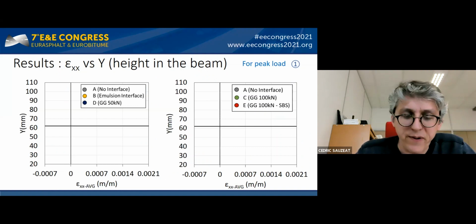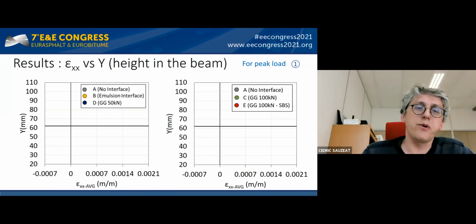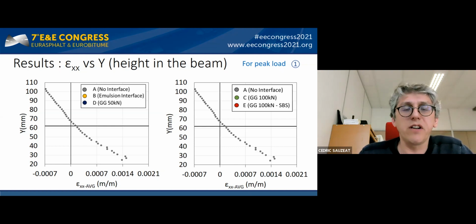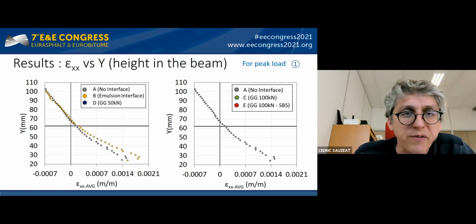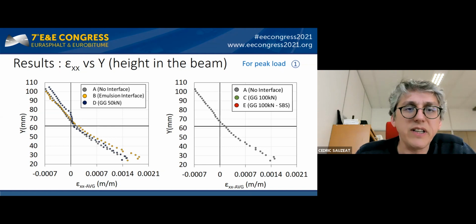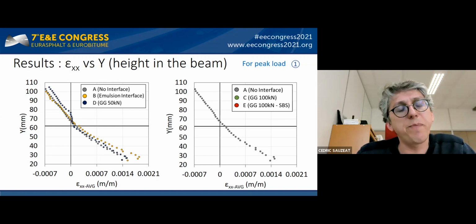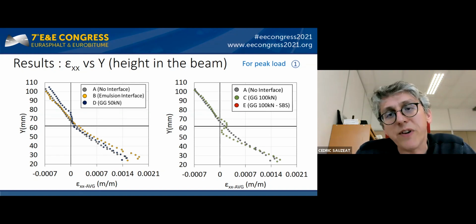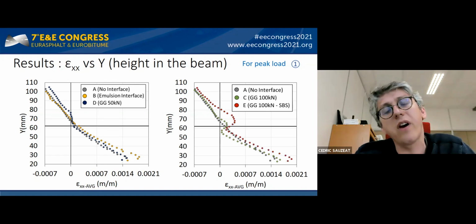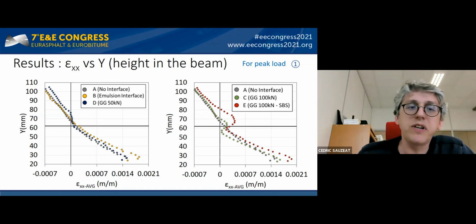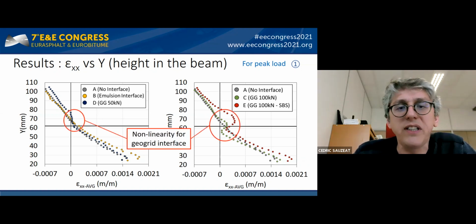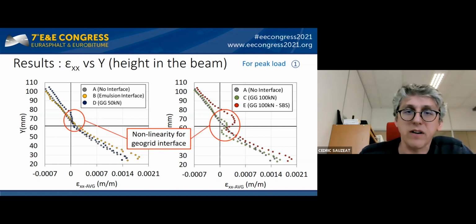We will analyze the difference in function of the reinforcement of the specimen. So you have here the result for the unreinforced specimen, and the result with an unreinforced specimen but with an interface. And here you can see what happened for the specimen reinforced with the geogrid of 50 kilonewton per meter strength, the same result with 100 kilonewton per meter strength geogrid, and the geogrid with polymer modified bitumen. You can see that the non-linear behavior happens around the interface during the propagation of the crack.